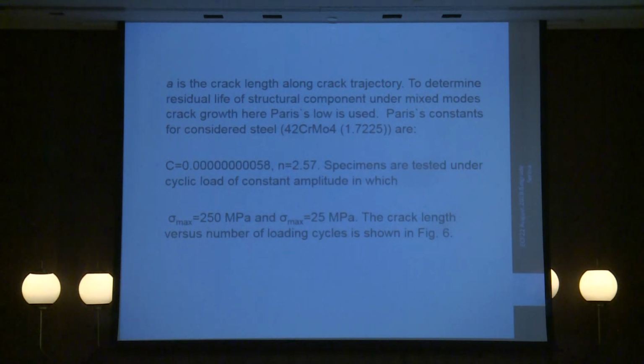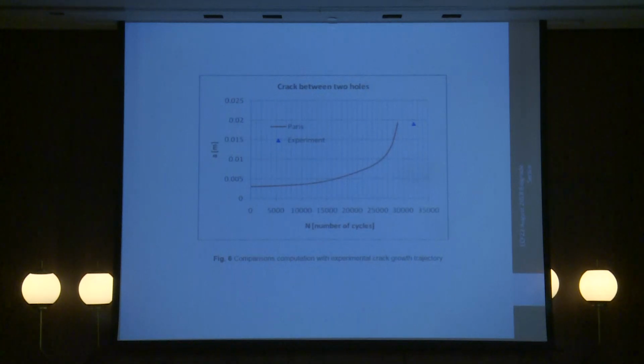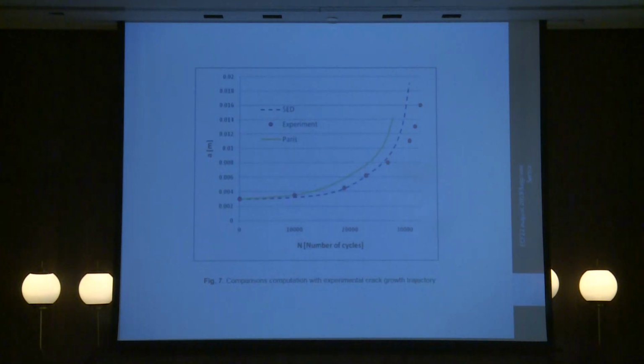We analyze crack length and crack propagation for this load. For the crack between two holes, like we had on the figure on the previous slide, we compare the results of the Paris method and the experimental results. Comparing the results of the strain energy density method, the experimental method, and the Paris law, we can see very good agreement of all three methods, but maybe a little bit better agreement between the strain energy density method and experimental testing.